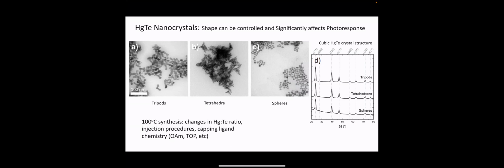Whereas mercury telluride nanocrystals with anisotropic shapes, so tripods, we call these tripods. So they're pretty interesting. These are branched nanocrystals of mercury telluride, and they seem to have a tripod structure. I'm familiar with tetrapods and octopods, but a tripod, like a planar tripod, is kind of an interesting shape. But these mercury telluride nanocrystals, that's what they tend to form. So the branch structures are tripods. We can also play some games with the synthesis and make tetrahedra, and the spheres.